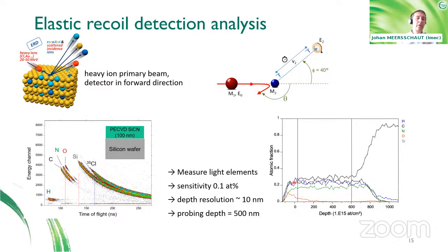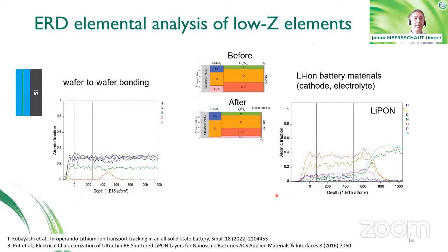So you have the atomic fraction in absolute numbers, 10 to the 15 atoms per square centimeter as a function of depth. So with this technique, you can measure the light elements in the sample with a sensitivity of the order of 0.1 atomic percent and a depth resolution of 10 nanometer. And it's important to mention again that this is an absolute measurement. By measuring the incoming particle fluence, you can determine the absolute amount of particles or atoms that are in the sample. So let's give a few examples on this approach as well.